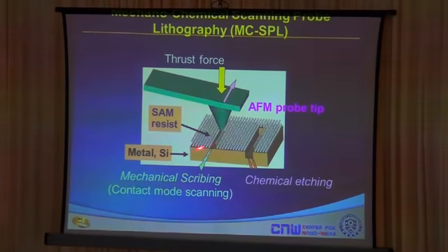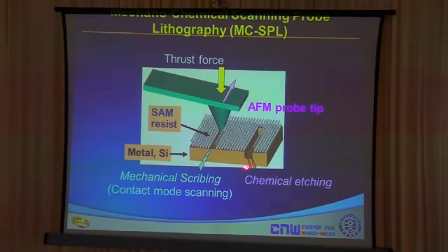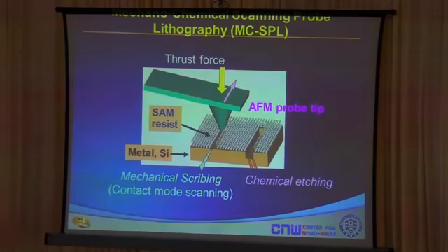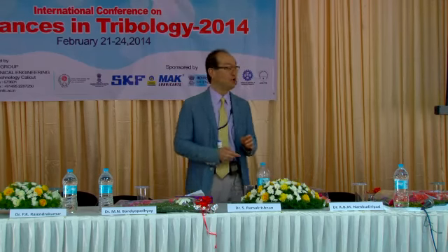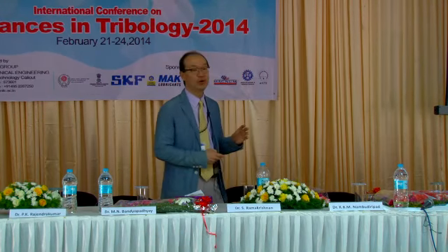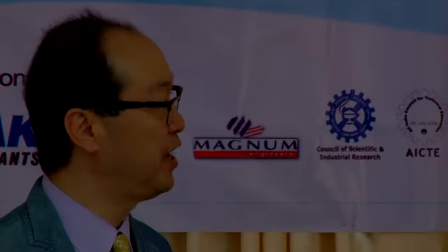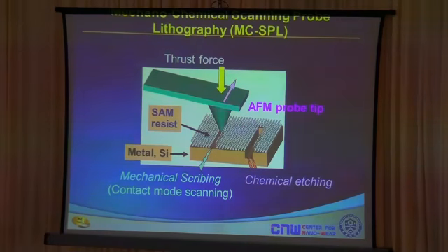So after mechanically removing the soft self-assembled monolayer with an AFM tip, we follow it with a second process of chemical etching. The first layer that we put, the self-assembled monolayer, will serve as the protecting resist in the etching process. So the exposed region will be etched and the covered region will not be etched. So after the chemical etching, we're able to create these very fine grooves.